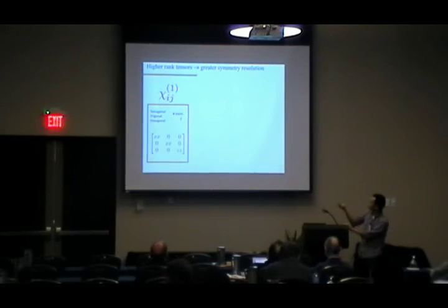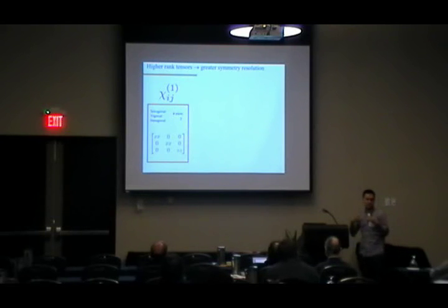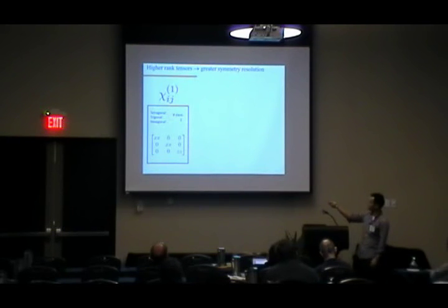Here's why nonlinear optics is quite nice. If you just look at the linear response, which is governed by these 3x3 tensors, okay, what you find is that by Neumann's principle, the symmetries of the crystal have to be embedded in the structure of these tensors. Okay, so in principle, if you know the structure of these tensors, you can back out the symmetry. But in linear response, you're limited by the fact that there are so few tensor elements. And so many different crystal systems give you the same structure, such that if you were to measure this to infinite accuracy, you still wouldn't be able to differentiate between certain types of crystal families. So for example, tetragonal, trigonal, and hexagonal crystal classes all give you a tensor structure that looks like this.